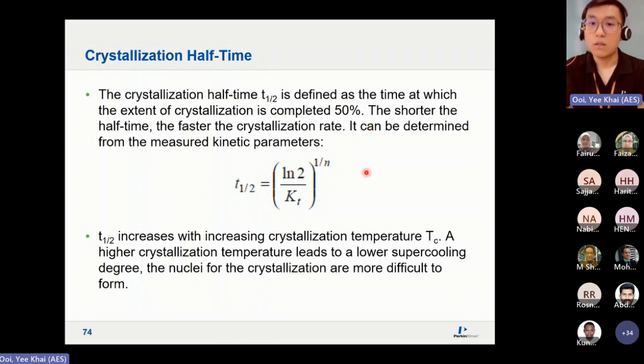So from here, with increased crystallization temperature, the T half increases, which means it takes a longer time at higher temperature for it to start crystallization. Okay. So higher crystallization temperature means lower supercooling degree, so the nuclei for the crystallization are more difficult to form.